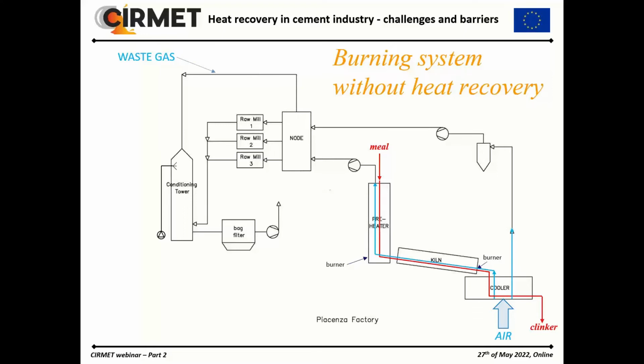But the remaining part are waste gases that we cannot send directly in the atmosphere because they are full of dust, and we have to clean them in the bag filter. But we cannot send the gas at 300 degrees in the bag filter. So we are compelled to cool them down in a conditioning tower by spraying water. So the temperature of the gases decreases from 300 degrees to about 150. There's a thermal loss, of course, in the conditioning tower.